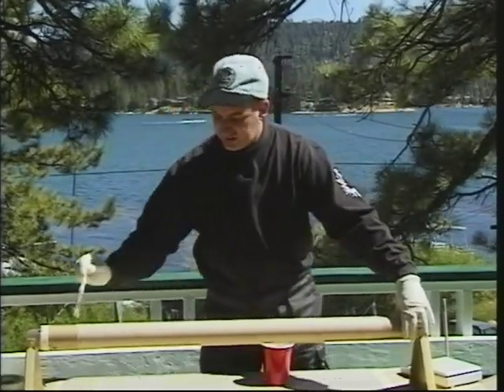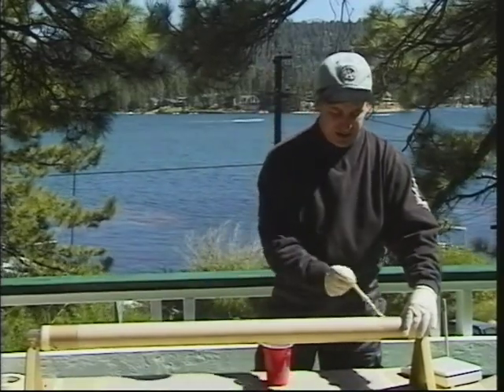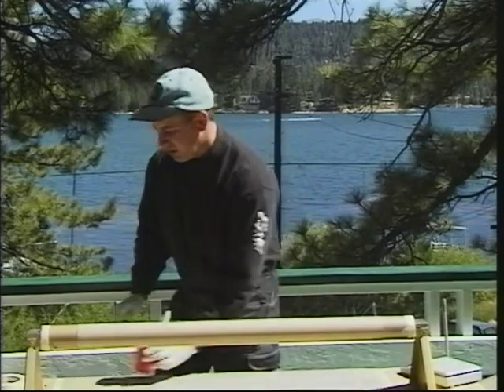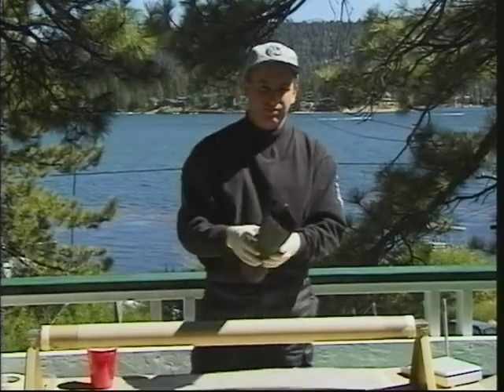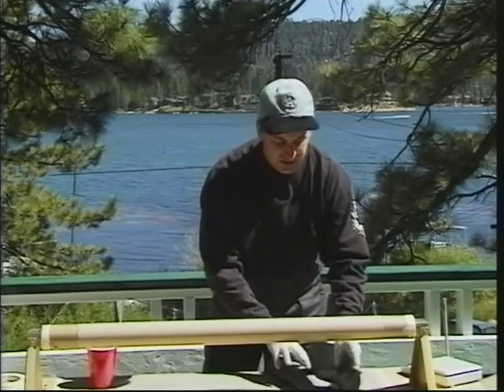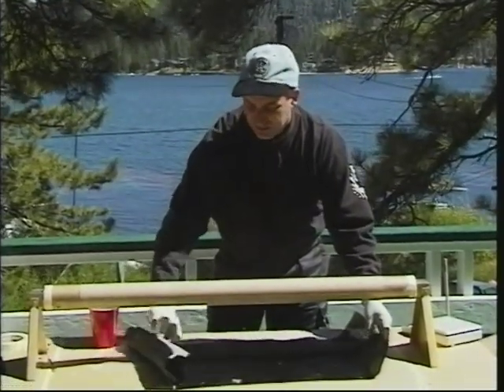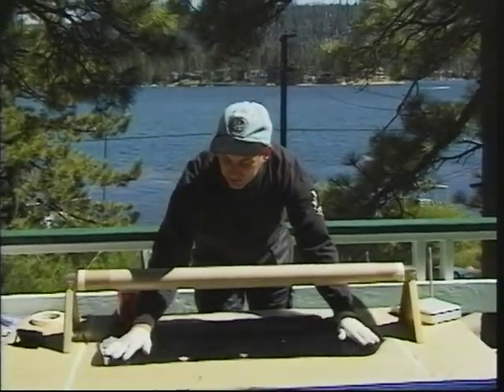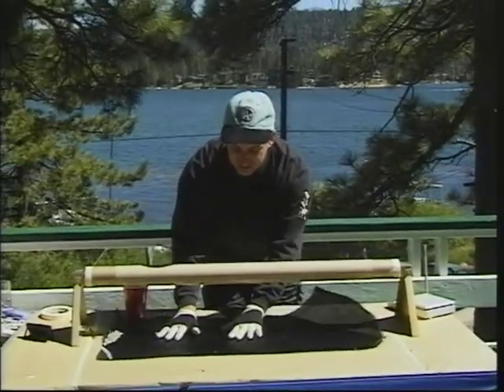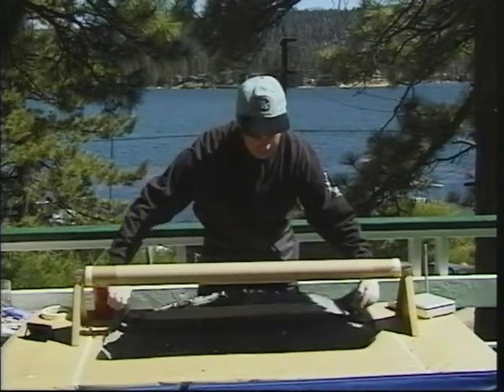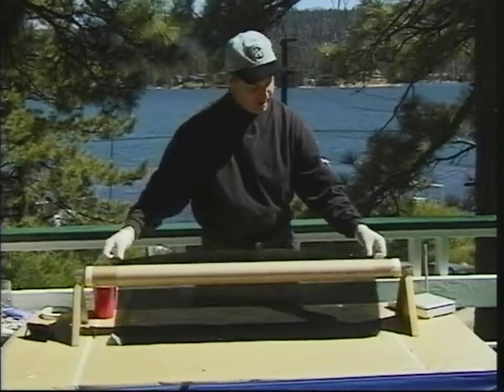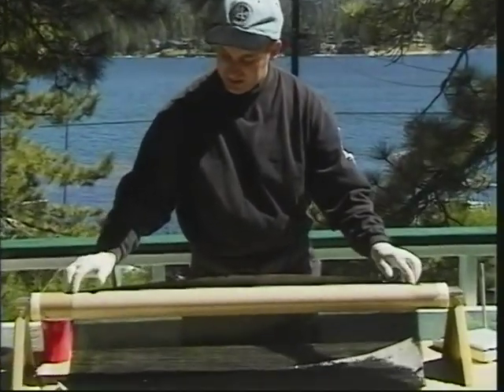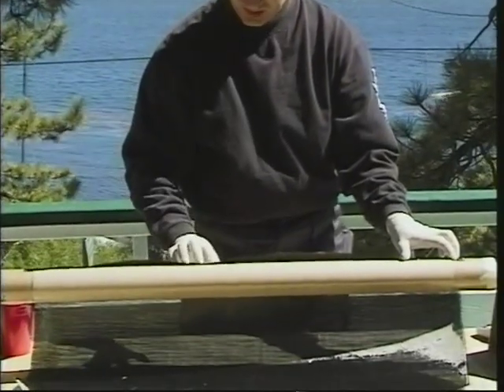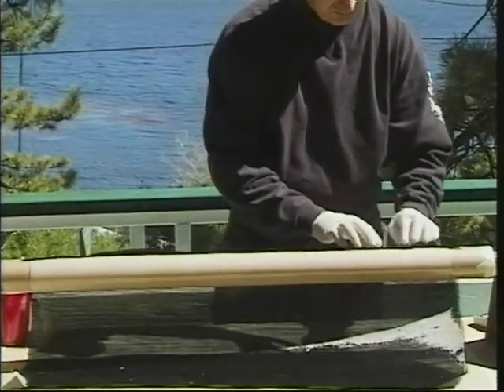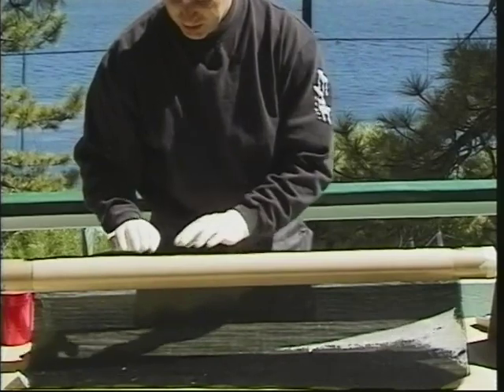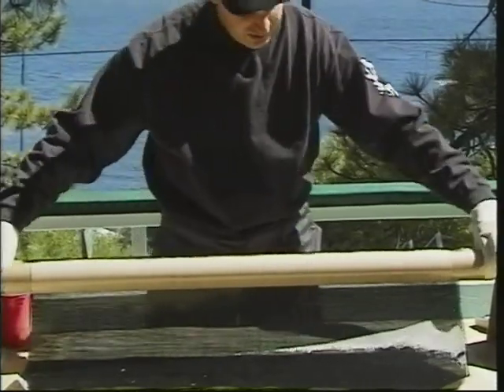Okay, so I've got the whole tube coated with resin now, and I'll grab my carbon. This is pre-cut again to give exactly 2 wraps right around this tube. You'll notice right off the bat that the cloth is a little bit stiffer to deal with. It's because the carbon fibers themselves are stiffer. So, same as last time, we kind of tack this onto the tube using our fingertips. And we're trying to get this on the tube nice and straight.